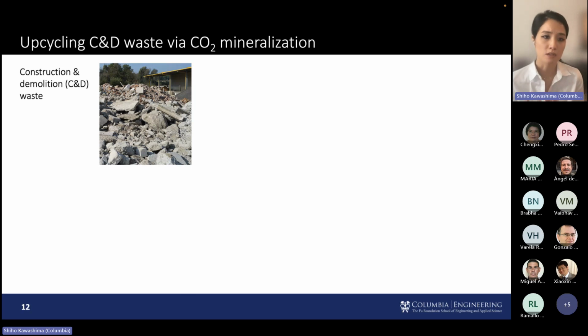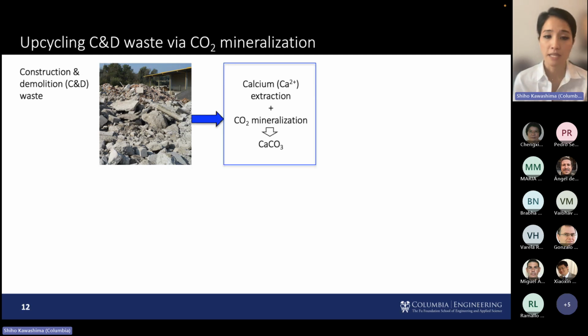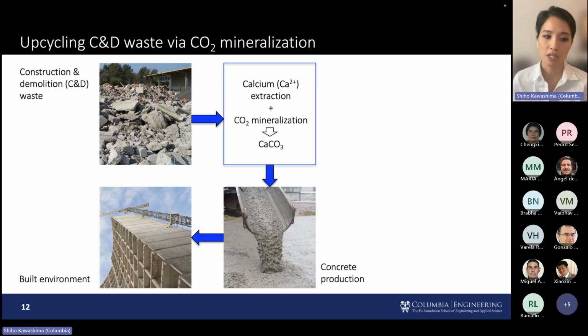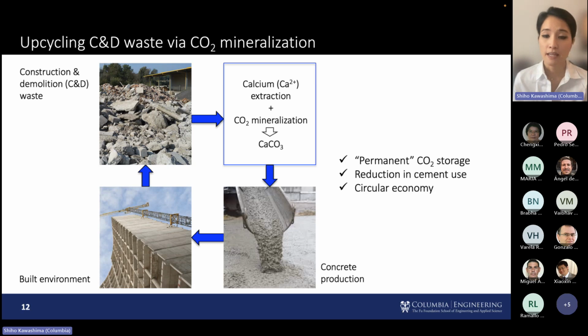So in our work, we looked specifically at construction and demolition waste, specifically the paste phase. And basically, we employed extraction and mineralization schemes. In a later slide, this will be shown in a little bit more detail. But we basically extract the calcium, because that's going to be in the recycled cement paste, and employ CO2 mineralization to produce calcium carbonate. So basically a limestone filler, and then that can be used for concrete production, incorporated into the built environment. And so this framework allows for essentially permanent CO2 storage, reduction in cement use because we're replacing OPC with this limestone filler, and a circular economy.